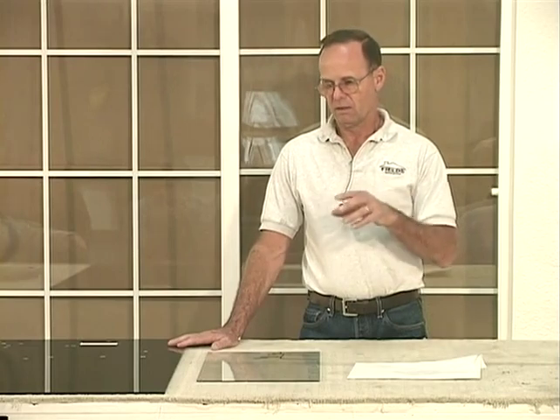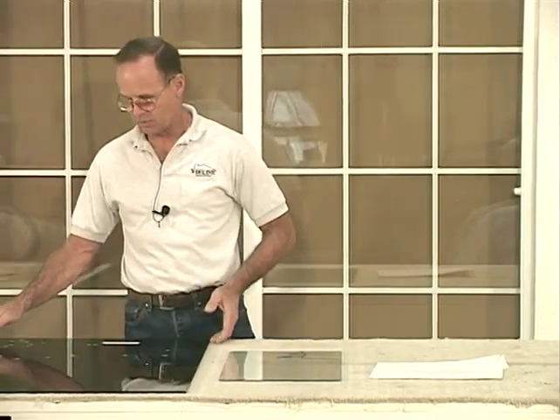If you use hydrofluoric acid or a product with hydrofluoric acid in it, you have a good possibility of getting tin etch haze. And that is caused by the reaction of that acid on that tin. You can try the exact same acid on the opposite side of the glass, and you won't get any reaction at all. And we'll have some slides later that show this piece of glass that we actually took pictures of.